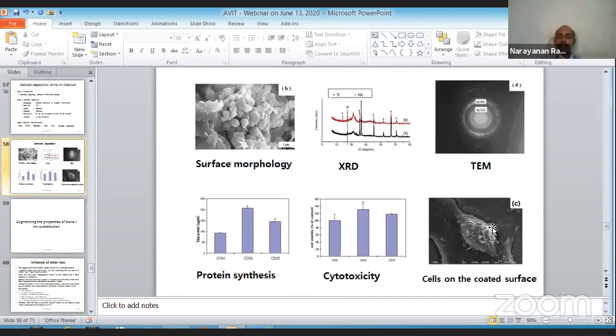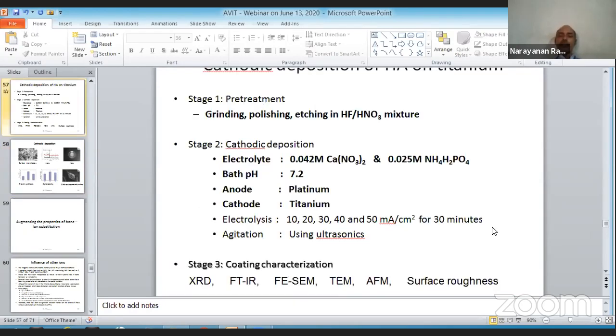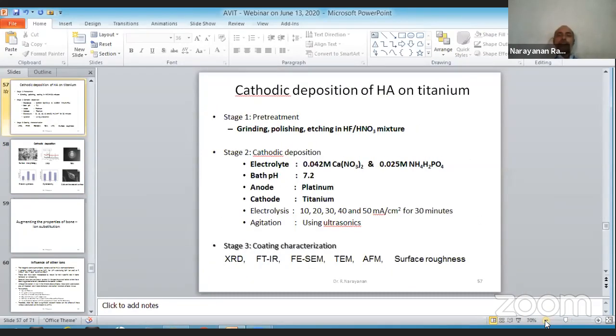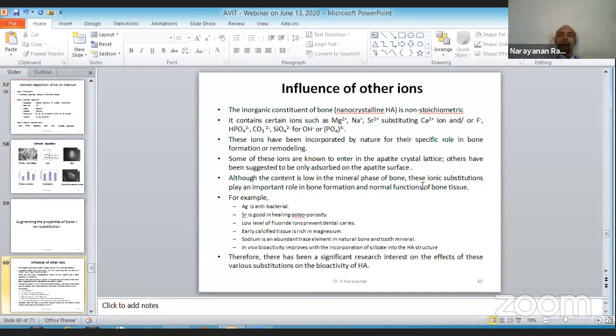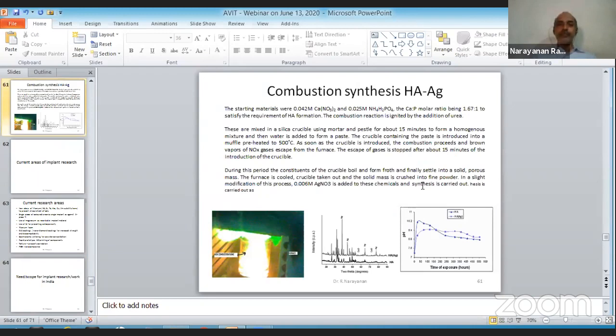So in this view, certain studies have been done in which silver has been used. In which silver has been added. So hydroxyapatite, which is a calcium phosphate, is augmented with the addition of silver, and you can see that the silver is present in XRD, and silver shows very poor dissolution. In other words, the silver substituted hydroxyapatite shows very poor dissolution compared to the absence of silver. That means the silver helps in stability. Silver is also antibacterial. This is one such study.